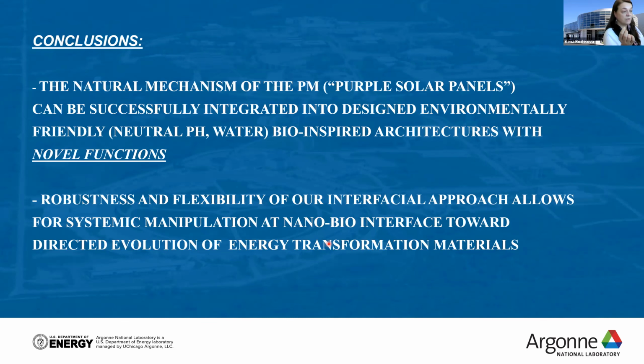It's also very important that this flexible approach allows us to vary reactions from hydrogen production to CO2 reduction. And very important also, if we compare with, for example, systems like isolated photosystem combined with inorganic platinum particles, these are just beautiful works in this area. However, isolated photosystem requires multiple cofactors, and actually it's a more expensive system than our minimalistic approach.